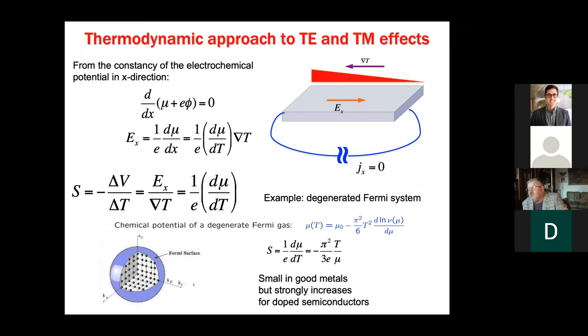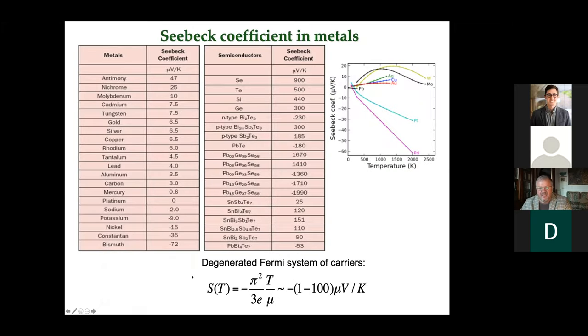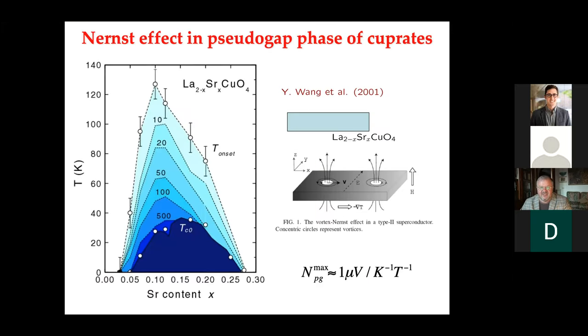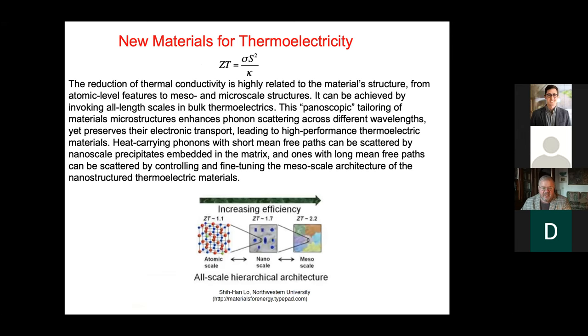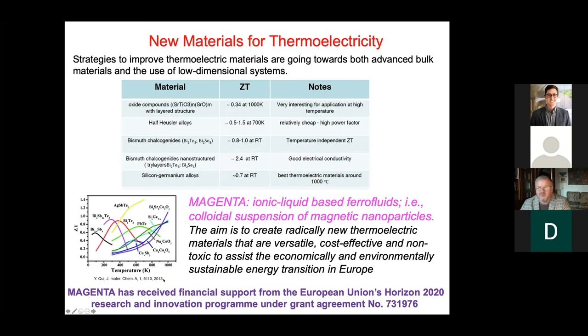And if you model the electrolyte even as an ideal gas with N 10^23, you will immediately see that we speak not about tens of microvolts, but about millivolts. So immediately we gain two orders, we increase the Seebeck coefficient by two orders, and the question is how to design these materials, how to make them stable and to use. Okay, so thank you very much. I hope that I'm in time.